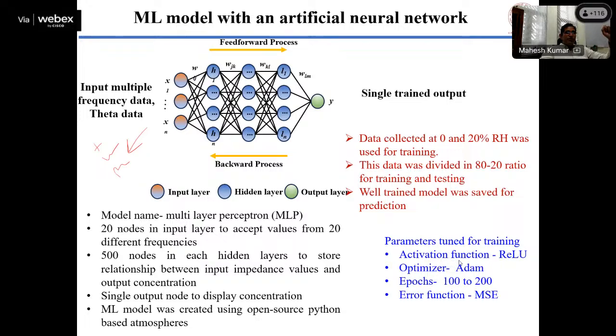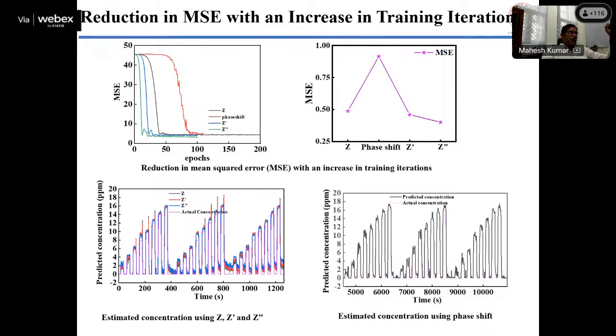We used an activation function, an optimizer, and epochs of 100 to 200, and the mean square error should be the minimum. So first we optimized all these parameters. Here you can see we optimized for each of these, and we try to minimize the mean square error as much as possible. Then here, in pink is the actual value and these are the measured values, the actual and predicted values.